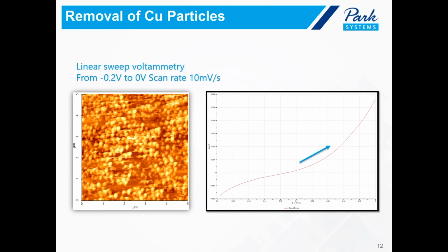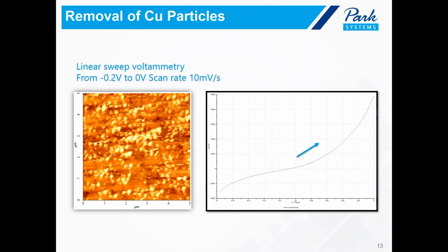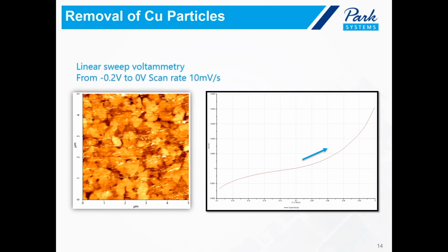So after the first sweep in the reduction process, we are now starting to see that some of the copper particles were removed, but still we cannot see the crystal terraces of the gold, since the majority of the sample surface is still covered with these copper particles. So we run again a second sweep with the same sweeping condition, and now we are starting to see more areas of the gold surface. But still, there are copper particles visible on the sample surface. So when we run another sweep with the same condition, this time the majority of the copper particles were removed, and we are starting to see a return to what we are expecting to see from the reference image, which are these crystal terraces of the gold.